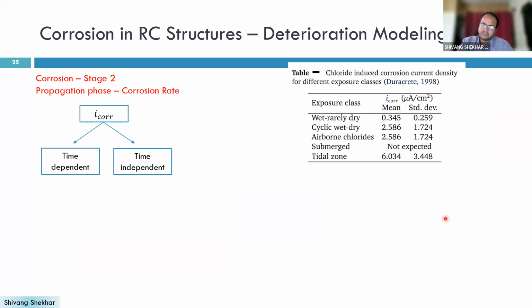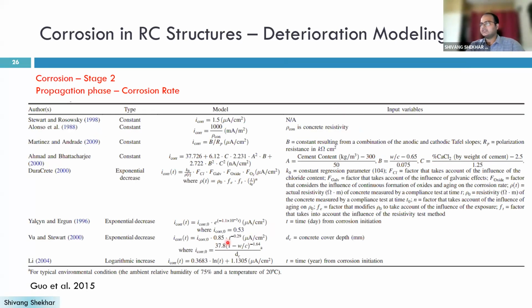Again here, we went to some of the literature available in renowned journals, and we have seen that for the corrosion rate, some researchers say it is a constant value, some say it is time independent, and some say it is time dependent. Like the document I was talking about, the DuraCrete document, based on exposure class, also gives the corrosion rate with standard deviation. Again, here there is uncertainty; we cannot work with a single number. So we have to take the uncertainty and then, based on this, try to find the area loss. There are some more, you can see, again from very good literature.